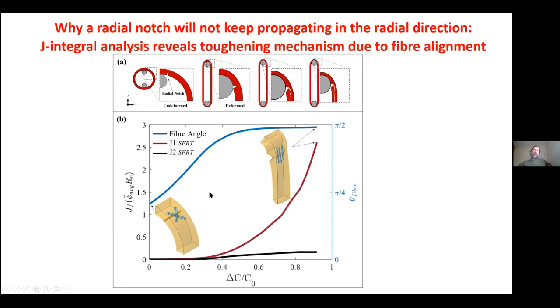And when we stretch the artery, these fibers become aligned in front of the crack tip like this. So we go from this alignment of fibers, we stretch the artery, and these fibers become very aligned behind the crack tip. And when they become aligned, it becomes harder to fracture them. Think about any fibrous material. It's very hard to grow a crack through the fibers. It's easier to grow the crack between the fibers or along the fibers, but not through the fibers, because it takes too much energy. So this is a toughening mechanism.